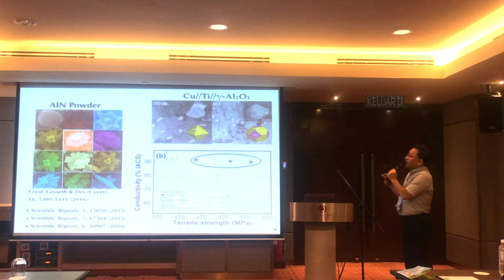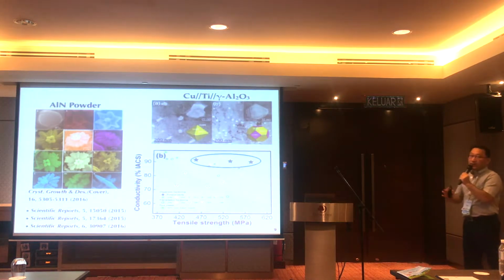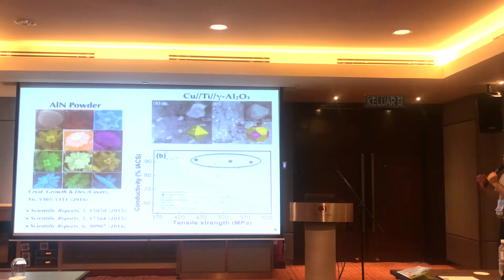For example, the target was: can we design a copper matrix that is very strong, also very conductive? There is a very strong conventional law that if you want to increase electric conductivity, you have to lose your mechanical properties. That's actually the governing law by conventional theory. But then we need a very good, careful design from atomistic levels. Otherwise, we cannot get over these conventional limitations. So we designed the matrix, and we dispersed gamma alumina nanoparticles, and also we dissolved a trace amount of titanium.